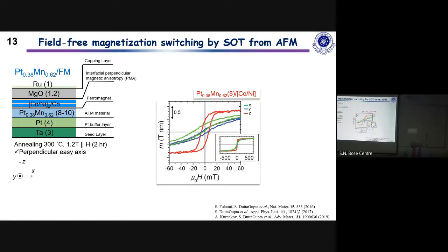So these are our magnetization curves at room temperature. The red curve is the one where we applied the magnetic field out of the plane of the sample, and you see that it has a magnetic easy axis along this direction. The blue and the green curves are the magnetization when the field is applied in the plane along two orthogonal directions. Here the green curve shows a shifted hysteresis loop, which means that there is the presence of exchange bias. This exchange bias field is roughly 10 millitesla.